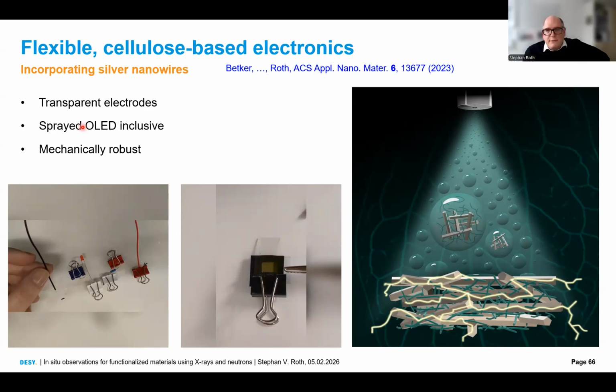Yeah, so first of all, we want to go away from silver. The problem with silver is the semiconductor industry is using it quite heavily, and they are using the majority of the silver stock. So what we actually want to do is go to copper, and you can create copper nanowires in alcohol. This is also mixable with cellulose. You can mix ethanol with water, and so cellulose with the silver nanowires or copper nanowires.